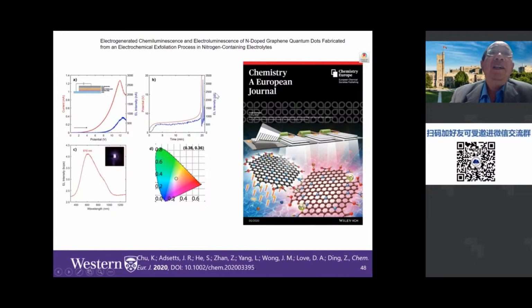As we said, we just prepare these graphene quantum dots and then get the light emitting electrochemical cell like this. Basically, it's 3 layers, and I already showed you the structure. And fortunately, we get the light emission from this kind of device, and that was really exciting. And in fact, from the CIE color diagram, it gives you the white. And the Chemistry journal liked our research and asked us to give an inside cover.